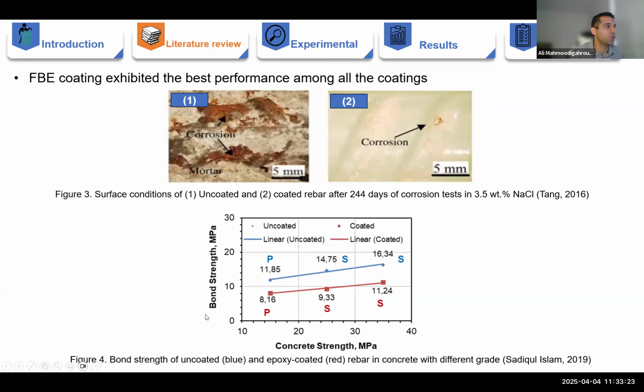Picture number 4 shows bond strength between uncoated rebar, blue line, and coated rebar, red line, for 3 different types of concrete. As you see, for all types, coated rebar shows lower bond strength compared to uncoated rebar. And this is because when you apply an organic coating on the surface of rebar, you make the surface slippery. Also, you change the surface chemistry from hydrophilic to hydrophobic, and concrete is hydrophilic.